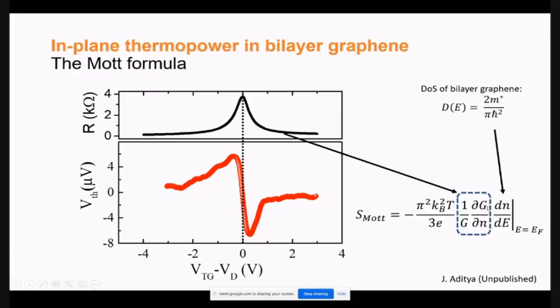So what happens is you can see the bilayer graphene has a standard parabolic band structure, the density of states is constant, and 1/G dG/dn comes from the experiment, and we can compute this number. Then you can see that the experimental value of the thermal voltage exactly matches what you get from computation. So that means bilayer graphene obeys the Mott formula very nicely. It's a semi-classical system per se.